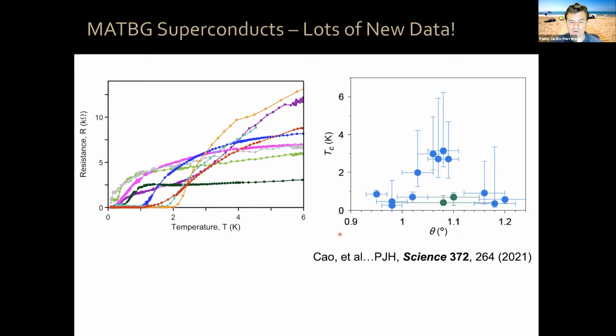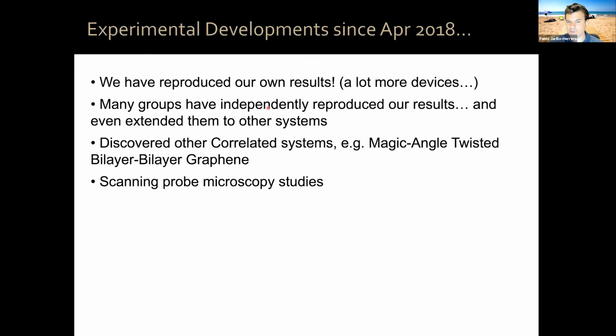Now, even better than you reproducing your results is when others reproduce it. And by now, many, many groups have independently reproduced our results and extended them to many other very interesting systems, okay? This includes very well-known work at Barcelona and at many other places. Now, we have also discovered many other correlated systems. For example, the second one, which was based on this twistronics platform, was magic angle twisted double bilayer graphene. So now we also have a structure with 2 layers, but each of these layers is a Bernal stack bilayer graphene.